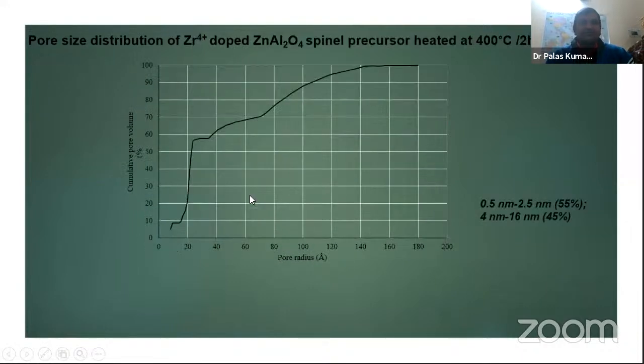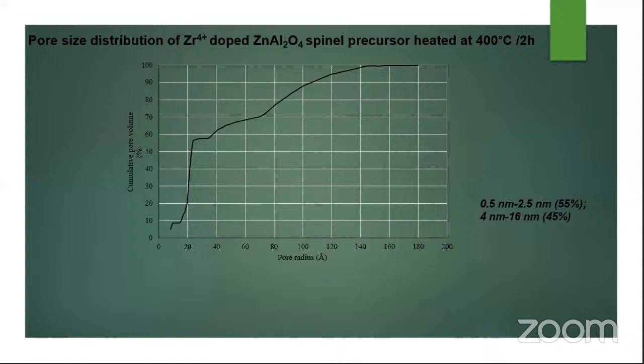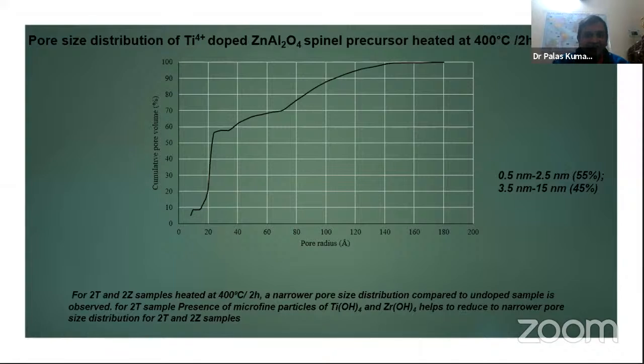Yeah. Thank you. So this is the zirconia. You see that the 0.5 nanometer to 2.5 nanometer is 55%, and 4 to 16 nanometer is 45%. Similarly for titanium. So this essentially means that for 2T and 2Z samples, due to formation of titanium hydroxide and zirconium hydroxide, which helps to reduce to a narrower pore size distribution of this zirconia and titanium doped matrix. This is quite a good sign.